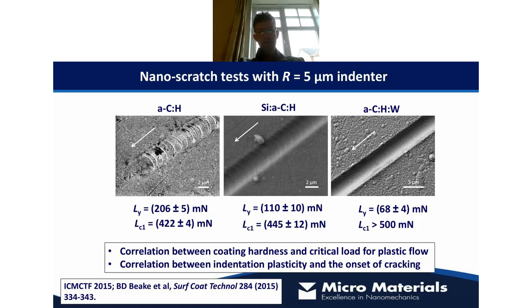So experimentally, if we do the scratch test on these 3 different hard coating diamond-like carbon systems with this 5 micron spheroconical probe, what we can see is that they're very different in terms of the LY, which is the critical load for the onset of plasticity, and the LC1, which is the critical load for the onset of cracking in these systems. The hardest coating system here has the highest critical load for yield. Conversely, this system here, the tungsten doped one, has a very low critical load for yield, but it didn't crack before the peak load of the nanotest system was reached in these tests. So there's a clear correlation between the mechanical properties of these coating systems and their behavior in these tests.